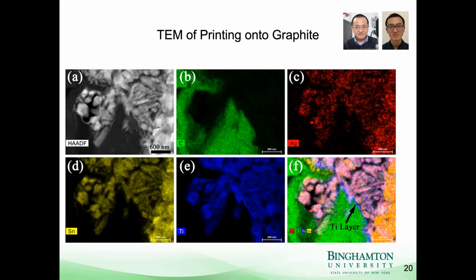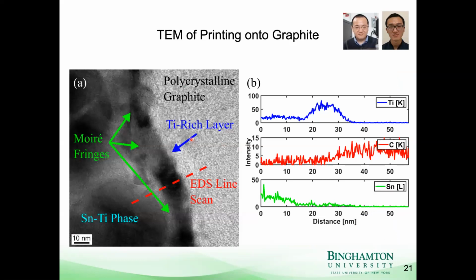So here's the titanium layer that formed at the graphite interface. So we think this is a titanium carbide film, and in the high resolution TEM here we can actually see polycrystalline graphite, and here's the titanium phase, and in between we can see some crystalline moiré patterns. We think that this is basically titanium carbide that's formed at this interface, because if you look at the titanium intensity, it has a peak about 10 nanometers wide right at the interface. So we think that a similarly thick layer also forms for the silicon, and having a very thin titanium silicide or titanium carbide layer, we think, is mechanically advantageous, because those kinds of materials are relatively brittle. So making them thin will make it more compliant.